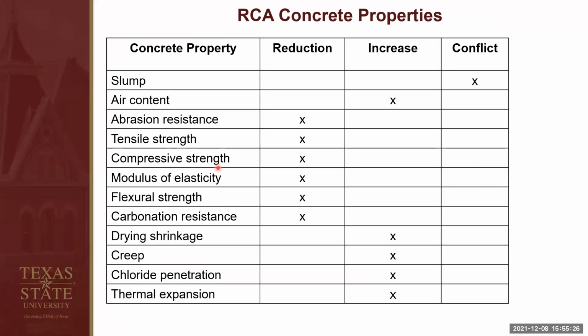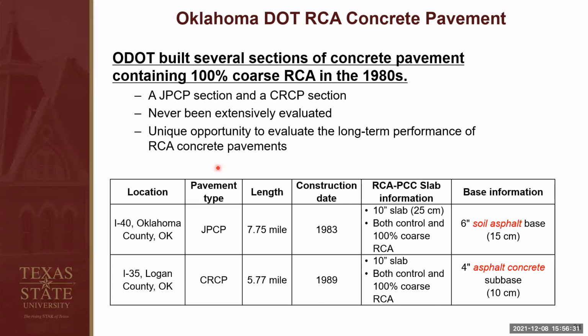So by adding RCA, recycled concrete aggregates, in concrete, our concrete mixtures will have different material properties. By adding RCA, the slump effect can be either beneficial or detrimental. By adding RCA, the air content will be increased because the RCA is more porous than natural aggregates. For the abrasion resistance, tensile strength, compressive strength, modulus of elasticity, flexural strength, and carbonation resistance, by adding RCA, those properties will all be reduced. And we will also increase the drying shrinkage, creep, chloride penetration, and also thermal expansion. So those are the lab results from the literature review.